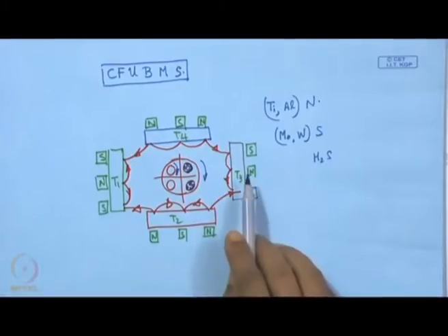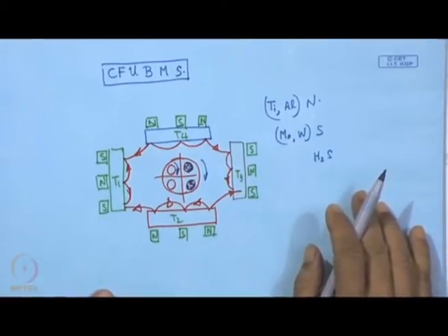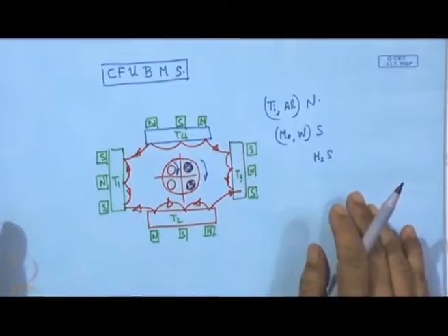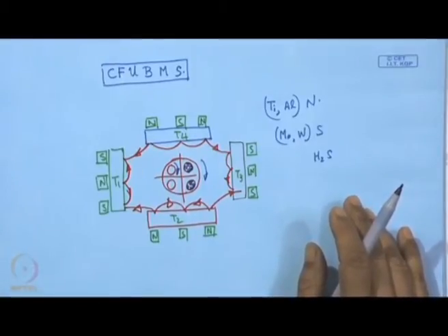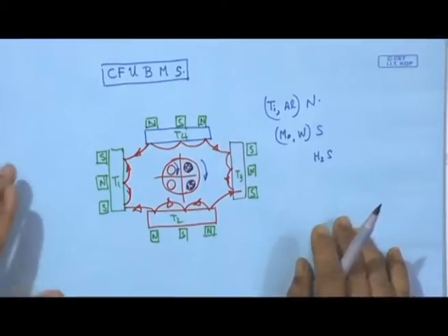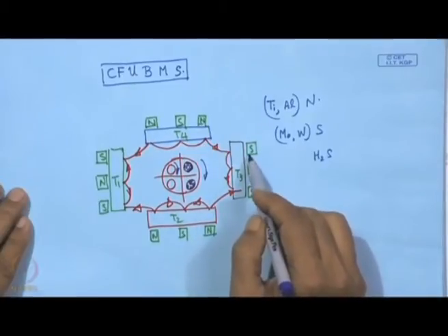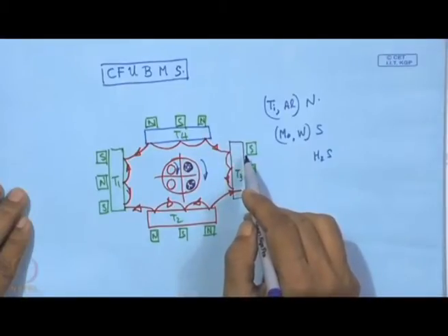When we have a fixed unbalancing, then the whole process has some restriction in conducting the process, and when we have some kind of flexibility, that means by using an electromagnet we can vary the field strength of the north and south poles, and thereby vary the degree of unbalancing.